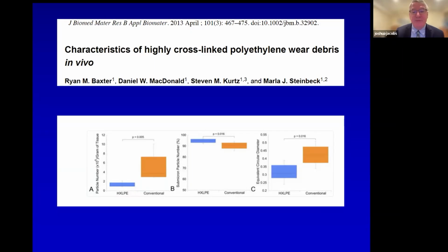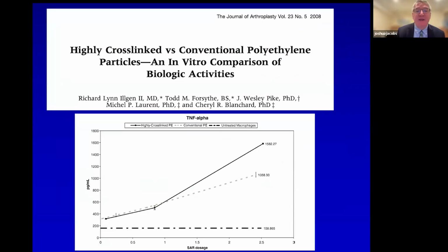However, the particulate debris from the highly cross-linked polyethylene may be a factor of 2 smaller than the polyethylene debris, and there are some studies that suggest that this smaller debris may be more bioreactive. This is an elaboration of TNF alpha, another pro-inflammatory cytokine. So there's this interaction between the number of particles and the individual bioreactivity of particles that has to be taken into account, so that we may not be out of the woods yet with wear debris causing issues, particularly for the knee.